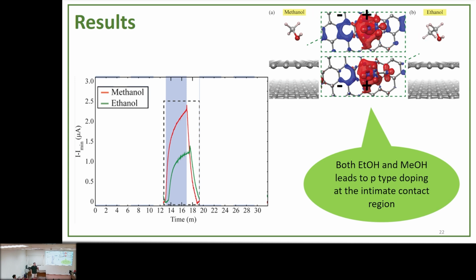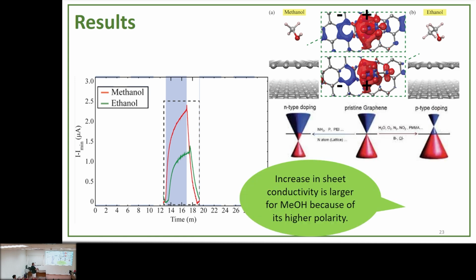Calculations say that methanol interacts with the surface more strongly. Why is it interacting more strongly than ethanol? Because of its dipole. It has a larger dipole. Since methanol has a larger dipole, it has more interaction, so there is more charge transfer for methanol. This is why. It's simple, and after calculations I can say so because we have confirmation. If you are working with graphene, this is N-type doping and this is P-type doping, and the increase in sheet conductivity is larger for methanol because of higher polarity. Higher polarity shifts the Fermi level more.